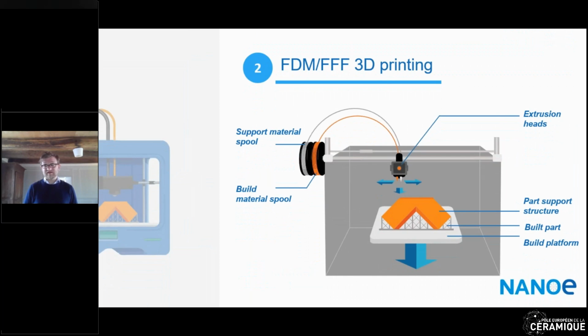Printing is really exactly the same thing as FDM and FFF printing. For those who are not familiar, FDM printing is made with a thermoplastic material. In our case, it's a mix of thermoplastic and powder in the form of filament, and this filament is pushed through a heated nozzle and melted. And we deposit the material in the melted phase, and it will cool down and make a solid part afterwards. We can also use a second nozzle to print with some support materials if we have some geometries which are not possible to print with just one material.